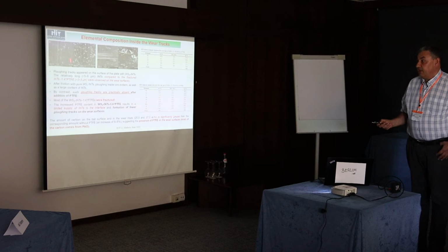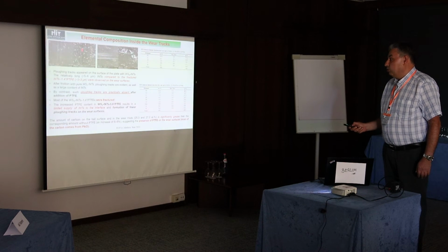These are scanning electron microscopy images of wear tracks following the friction. So with the pure nanotubes, you can see these plowing tracks appeared on the surface of the plate, and these are undamaged nanotubes inside the tracks. But after friction with nanotubes covered with Teflon, we see that there is some fracture of nanotubes. So fracture is not always bad. And these fractured nanotubes enter into the surface in the contact area, and in such a way they reduce